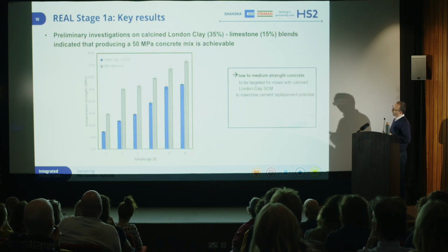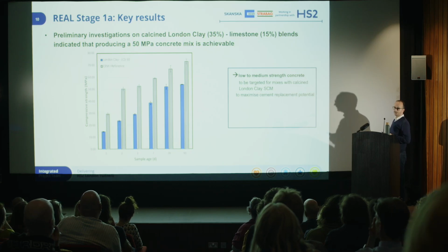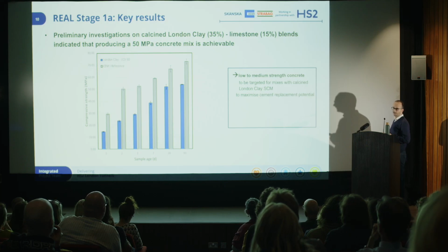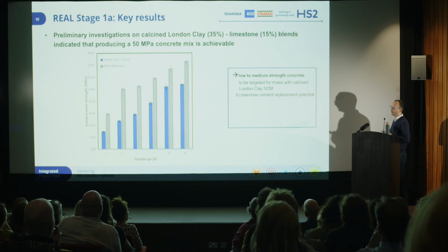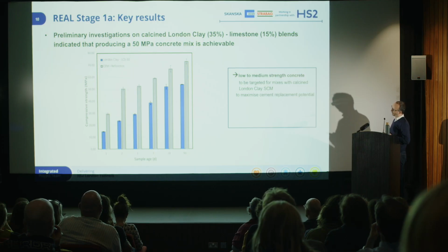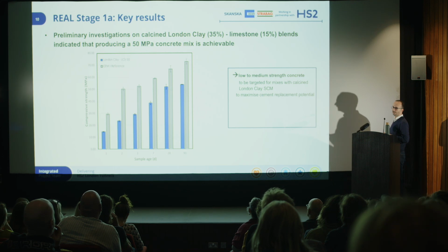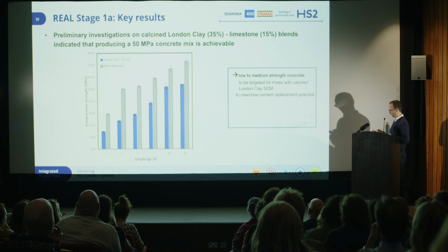We did some lab trials just to see what is going on, and there you will see the LC3 reference. LC3 is something that the EPFL team in Switzerland have developed. It's the limestone calcined clay cement, the 3 Cs. And this is what we started looking at. You can actually get high strength development on low reactivity clays, which was surprising.